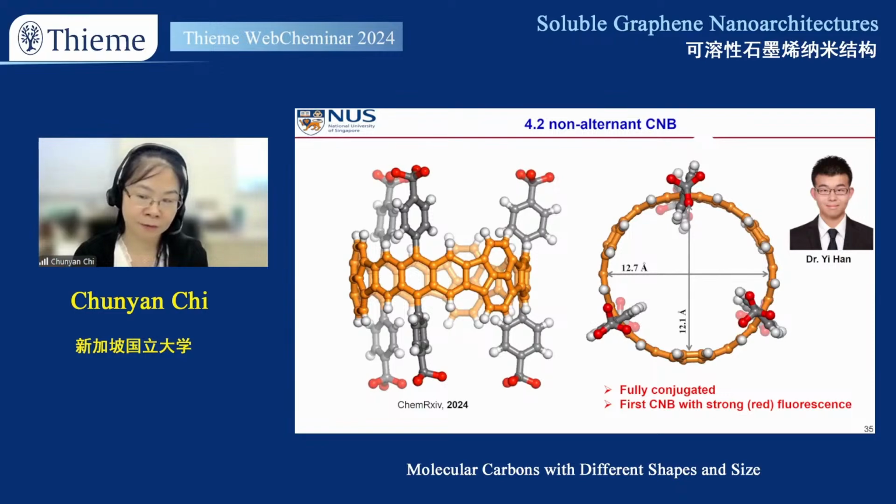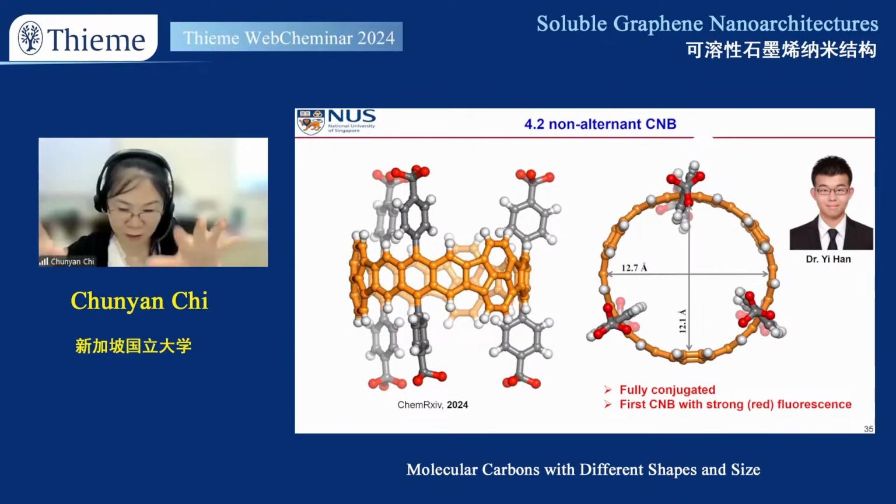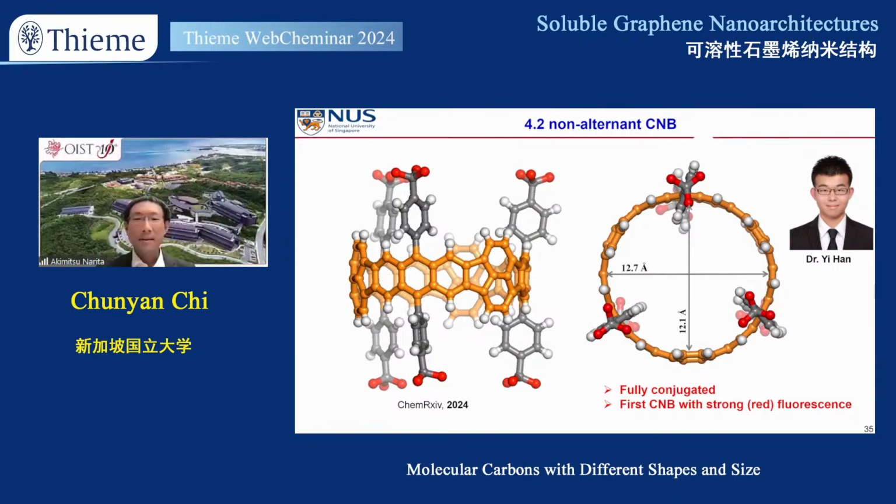At higher temperature, the NMR peaks become broad and the ESR intensity increases. Similarly, when the molecules have a large diradical character, at room temperature the NMR peak is already broad and the ESR intensity is also already very high. I see. Thank you very much.